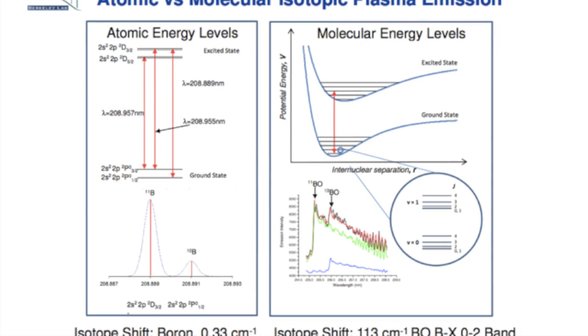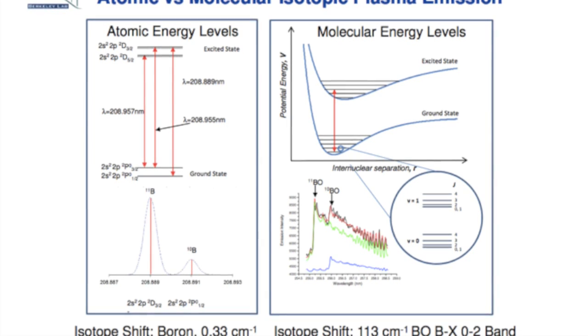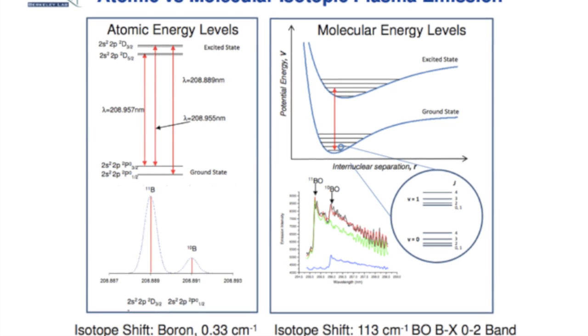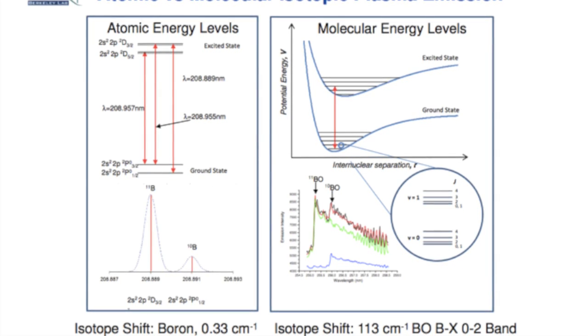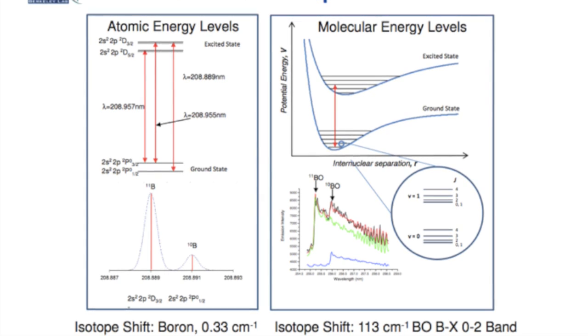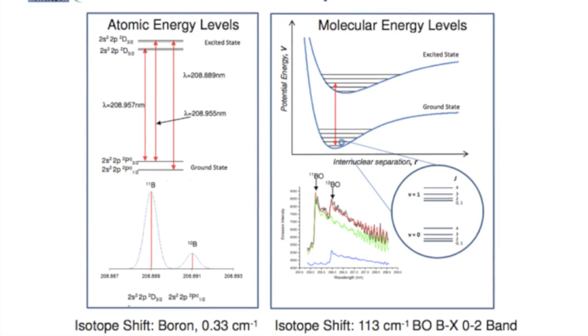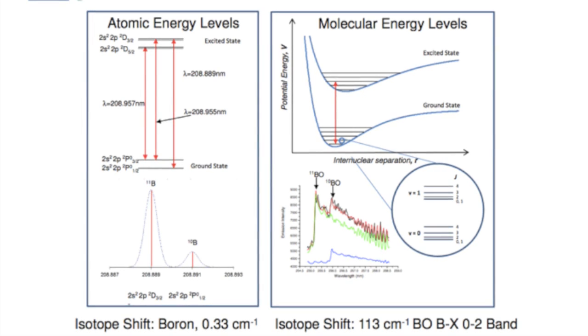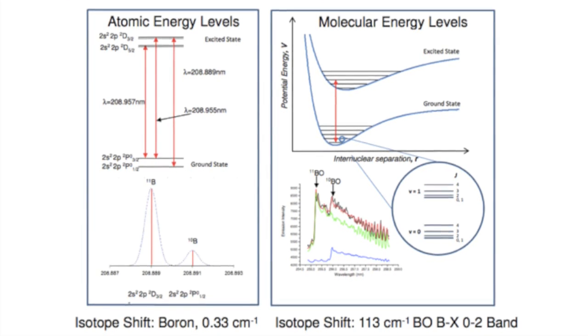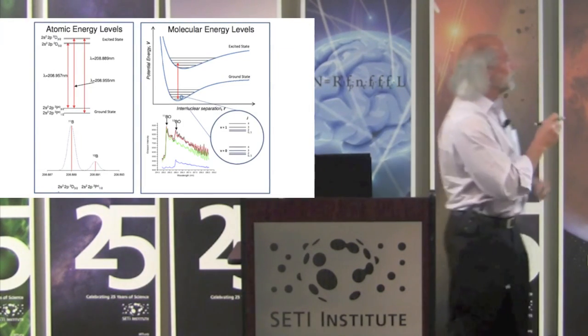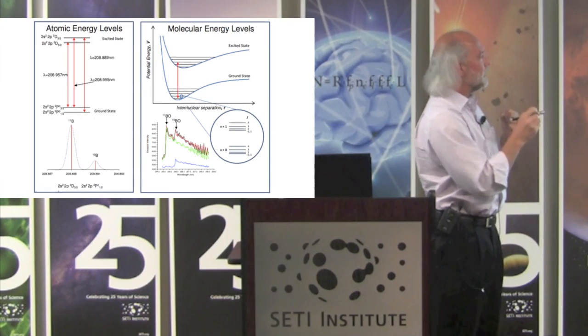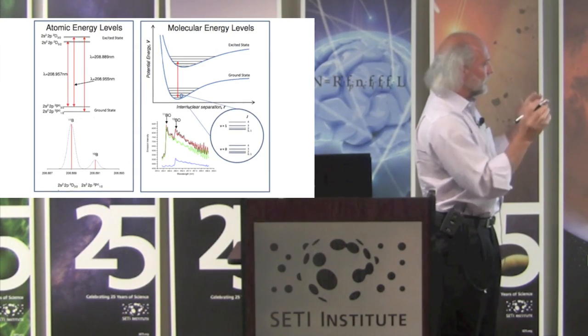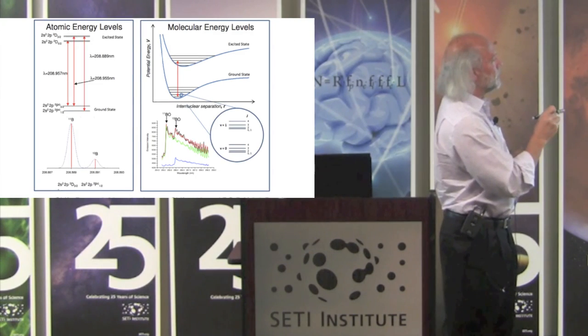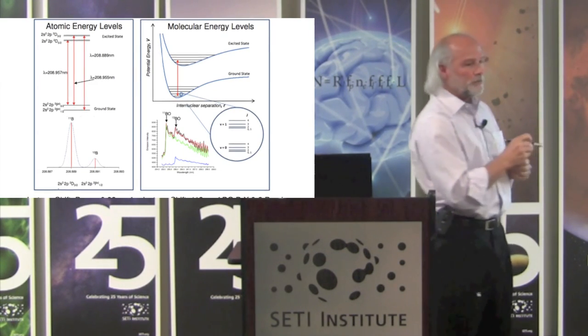Very small, right? This is 208.889, wavelength 208.891. So there's 3 picometers, 2 picometers, I can't count, I need a calculator. So 89 to 91, the distance between boron 10 and boron 11, if you were looking at atomic transitions, which is what we traditionally did in LIBS plasmas. However, if you look at the energy levels for a molecular oxide, you have the reduced mass, which gives you this sort of distance thing, where the two atoms are when they're vibrating. Then you have all the vibrational states, and on top of the vibrational states, you have rotational states.